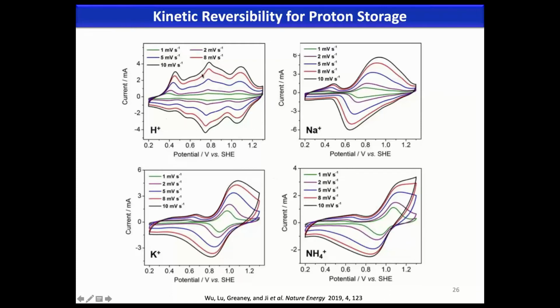we can see protons, and we still have that nice structure. For capacitive materials, for capacitors, I don't think we always have to look for rectangular shapes. Rectangular shapes are good and could be nice capacitors, but just having peaks vertically aligned is a very strong sign that your reaction is really fast. For protons, we do have this. For sodium, potassium and ammonium, we don't have this luxury. They are very sluggish. And here the electrode material is exactly the same.